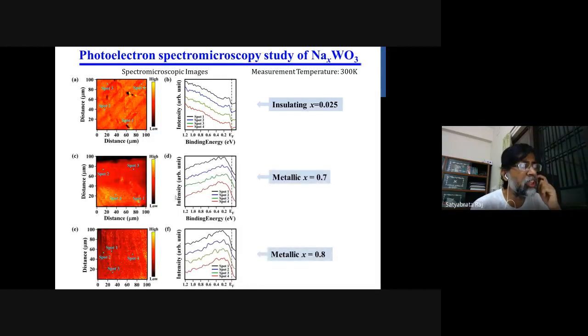Whereas we have done the similar for the 0.7 and 0.8. 0.7 should have 70% metallic character and 30% insulating character. But this gives a fully metallic density of states at the EF. So that means the sample is fully metallic throughout.